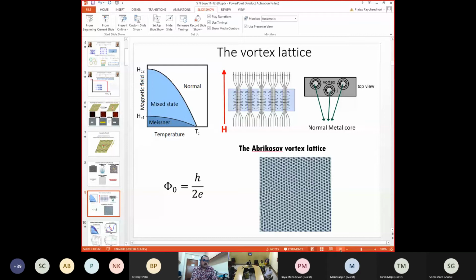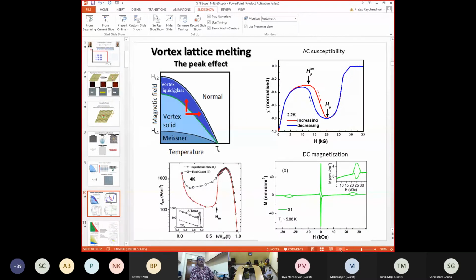Now, this is how a flux line lattice looks like. This is how the vortex lattice looks like, and how we get such images I will tell you in a moment. All right, now this kind of a vortex lattice behaves like a solid because you have these vortices that are like small bar magnets with the same polarity. So therefore they repel each other, and this repulsion normally arranges this vortex lattice into a hexagonal lattice, and that is what we know as the Abrikosov flux line lattice.